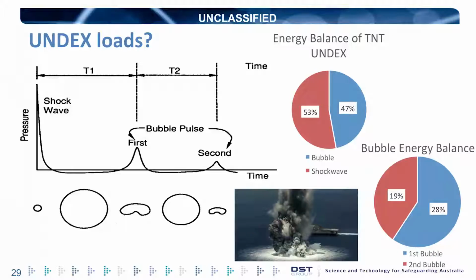So what happens when we do UNDEX trials on ships to test this? We tend to bring the explosion away from the ship so the water plume misses the ship, and we measure the resonance, we measure the hogging and sagging of the ship under these loads. For a certain size of UNDEX, generally about 50% is the initial shock wave, but 50% is the bubble loading afterwards, and then the second bubble is a smaller percentage. So that's going on underwater.